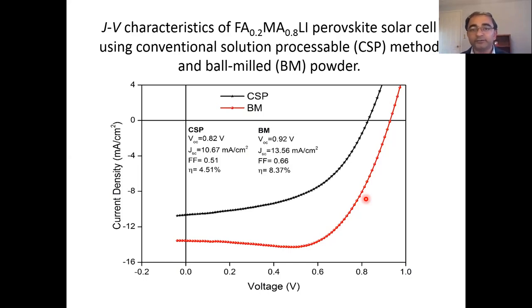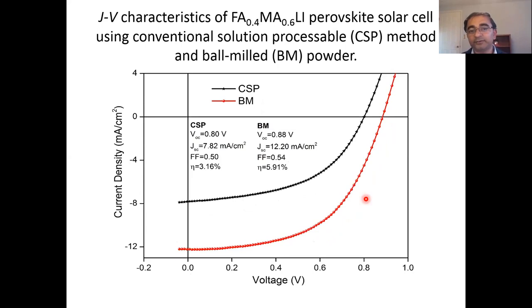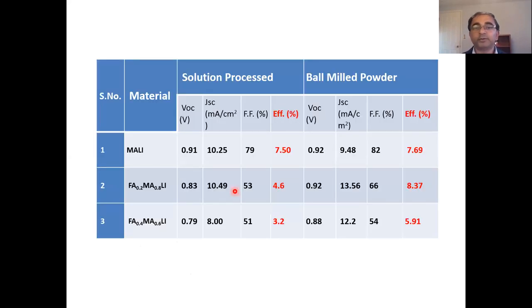In that way, we can enhance the efficiency of the devices. You can see from here, this is another batch of devices. These are the photovoltaic parameters which we have found, this is the solution process which most people are using, and this is the ball milled powder which I have made. You can see that all the photovoltaic parameters, this VOC is 0.92, very close to the ideal value. When you compare with conventional techniques which most people in the world are using, we got higher efficiency with the help of the powder which we have made.